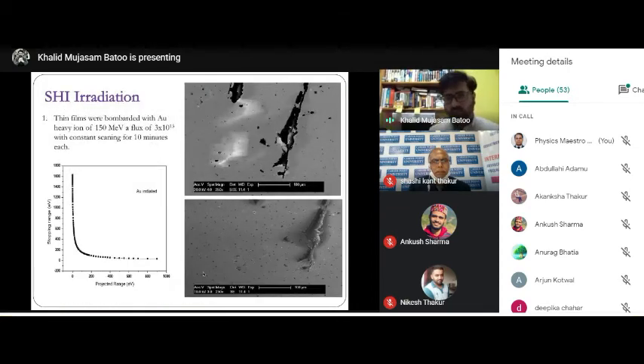So what we did, we irradiated the film with 150 mega electron volt using the IUAC facility at New Delhi. We scanned it for 10 minutes, 1 centimeter square, with a flux of 3 into 10 to the power 15. A gold ion beam was used.